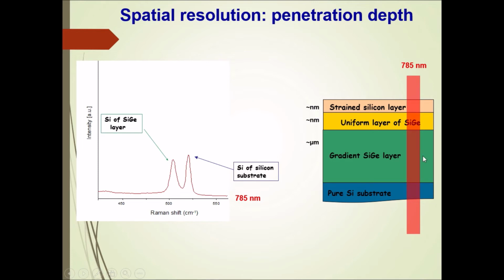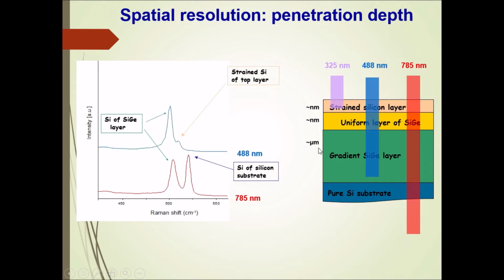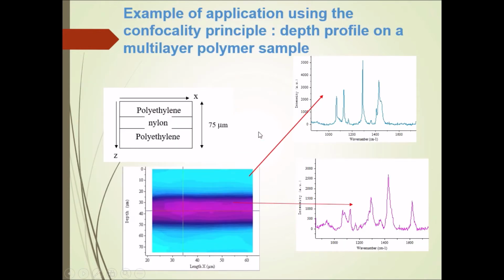Using different kinds of lasers with different wavelengths, we have several penetration depths. Longer wavelengths, like in case of red laser, penetrate more, so they can reach lower depths. In this case we have a silicon germanium layer, uniform silicon germanium, and strained silicon. So with different lasers, we can go to different depths, and we can identify the composition of the layers. Here is another example, where we have different polymeric materials in a film. We have polyethylene, nylon, polyethylene. So also we can distinguish that this top surface is polyethylene and this middle one is nylon.